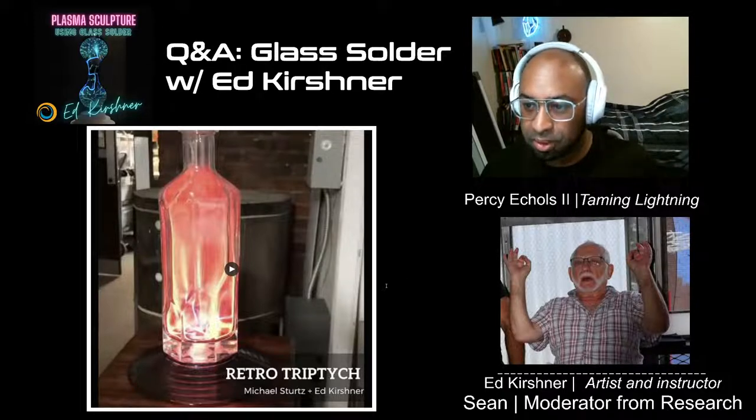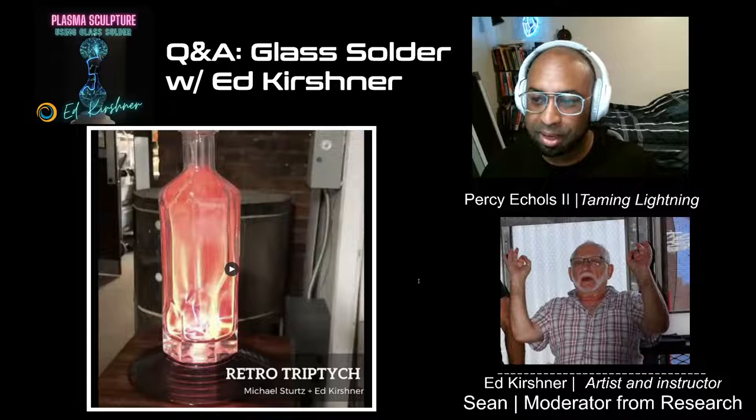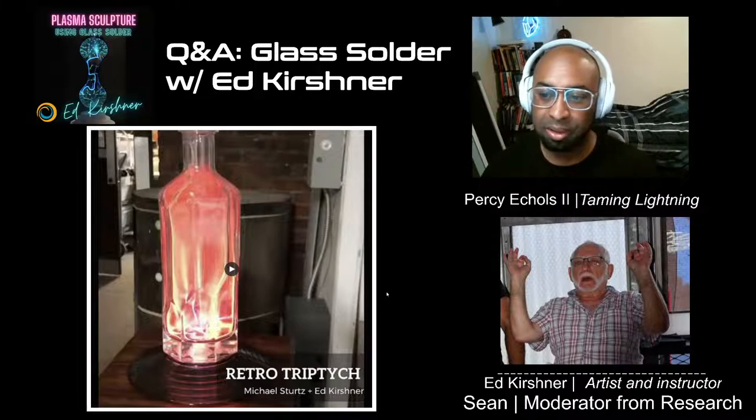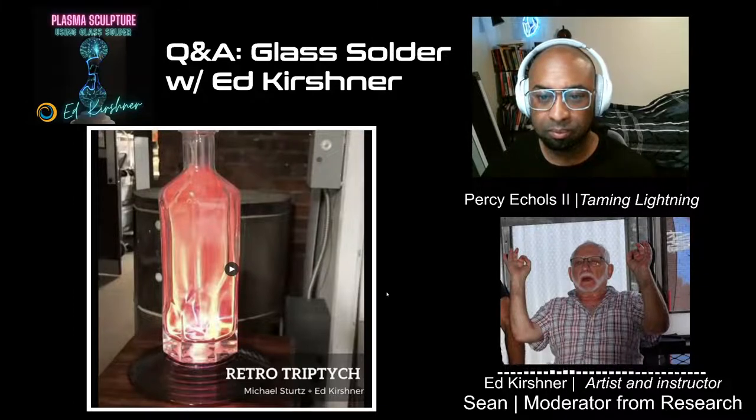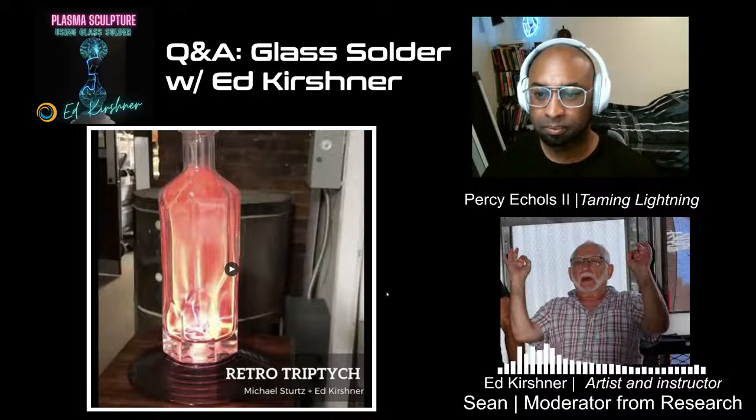His question is just about the kiln fired enamel. Do you mix it with something to make it a paste? And how do you keep the glass vessel from slumping at kiln temperature? The solder melts at a lower temperature than the annealing temperature of the glass. So it's made explicitly so that the glass will not slump. That was the whole idea of developing the solder.